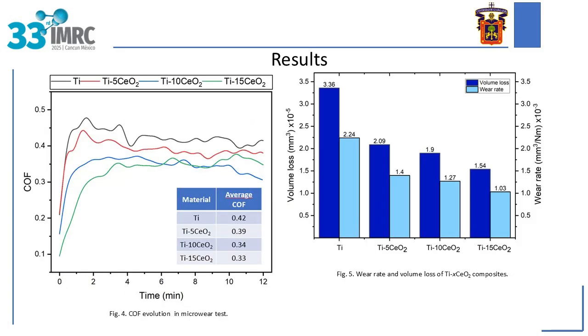The dry micro-wear test allowed us to determine the friction coefficient of each sample. In all cases, a rapid increase was observed in the initial stage of the contact between the alumina ball and the samples. After 2 minutes, the test stabilized due to the accommodation of the surface roughness. This adaptation to the shape of the contact decreases adhesion forces.